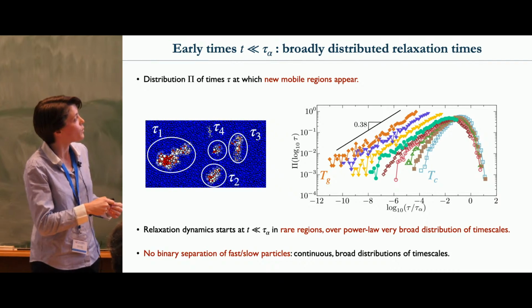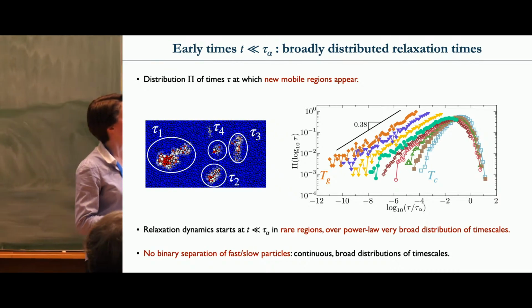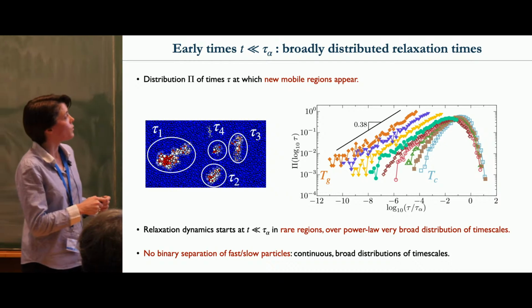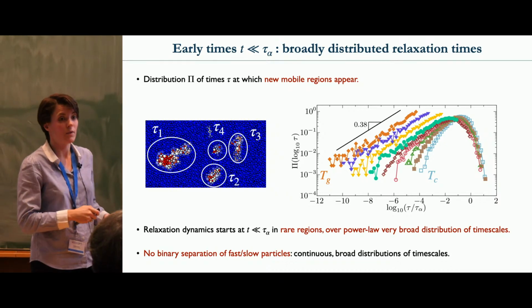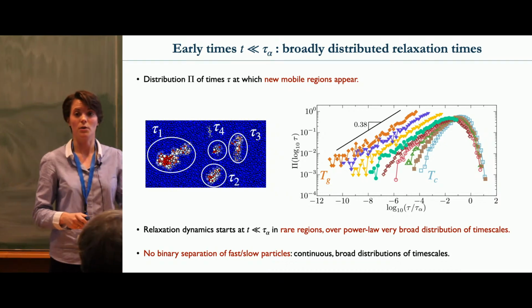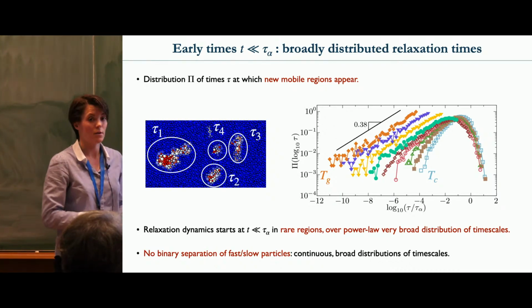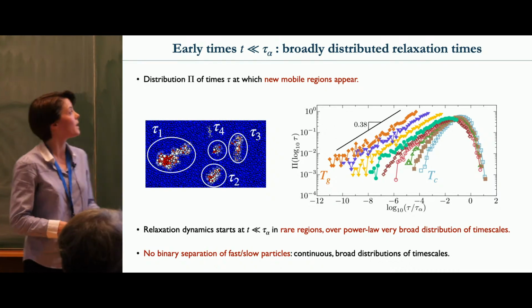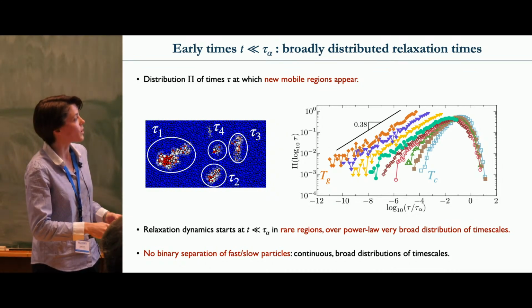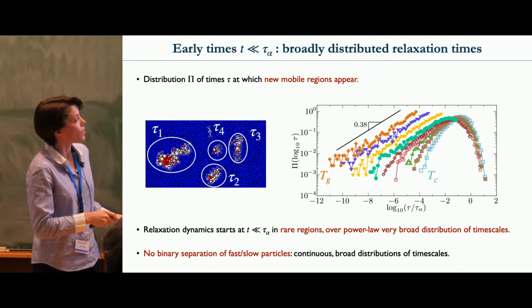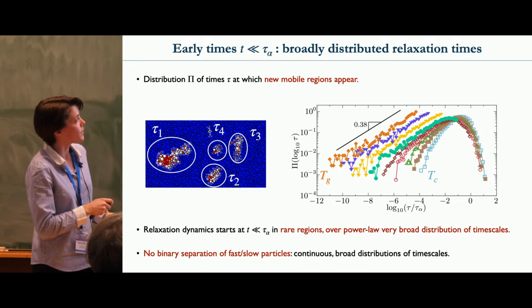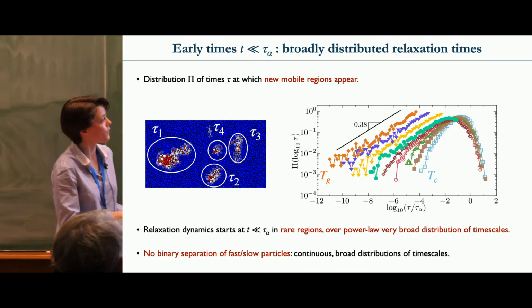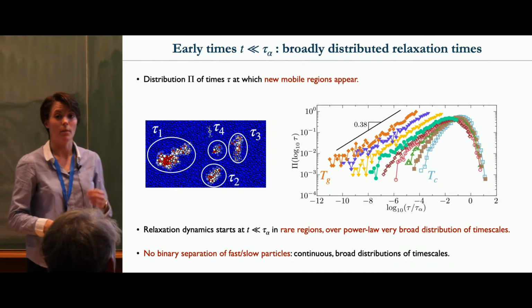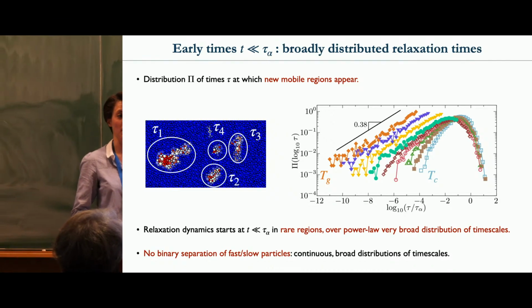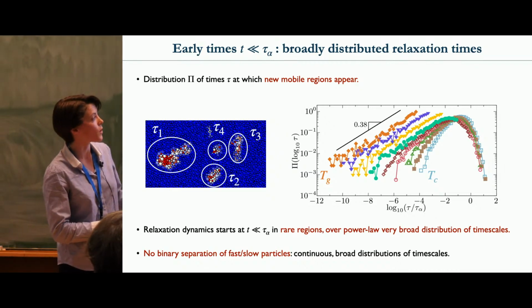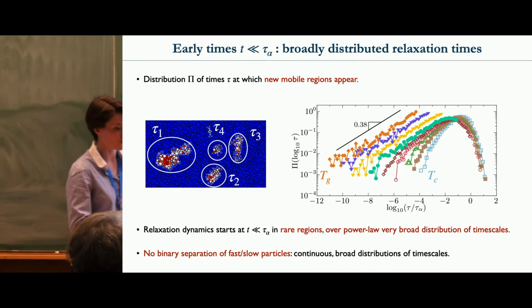Here I have a few clusters observed at very low temperature. We measure the time, tau1, at which the first cluster first appeared, and then for each of these clusters we record the time at which they appeared. Then we construct this distribution: the distribution of the time of apparition of these mobile clusters. We rescale everything by tau alpha because this increases dramatically as a function of temperature, so this allows the comparison between high temperature and low temperature.